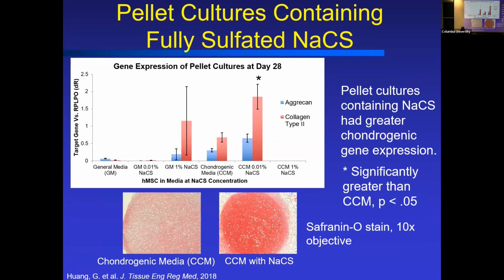So shown here, we first investigated that with the fully sulfated cellulose sulfate. We put that in culture media. We ran those cells in pellet cultures, and we noticed that the cells will become chondrocytes more readily in the presence of that fully sulfated cellulose. We can perform histology, and shown down on the bottom there, those cells look much more homogeneous and have that chondrocyte morphology in the presence of the cellulose sulfate and express the right markers.